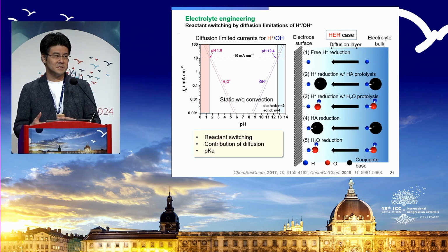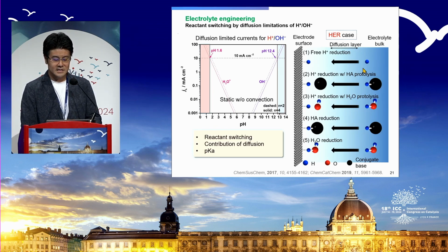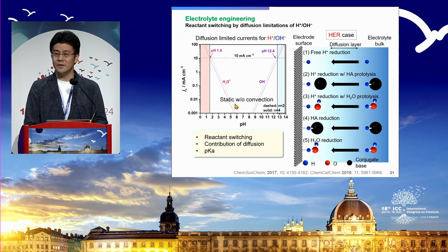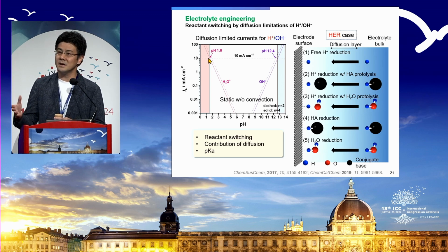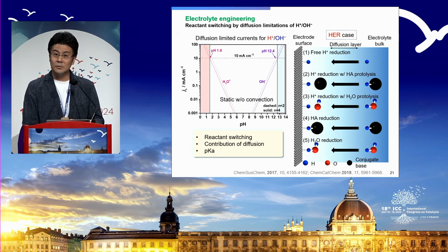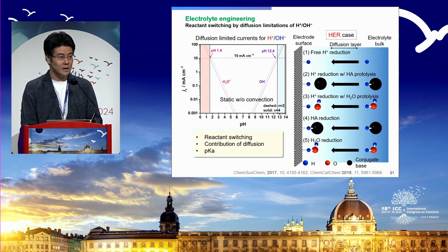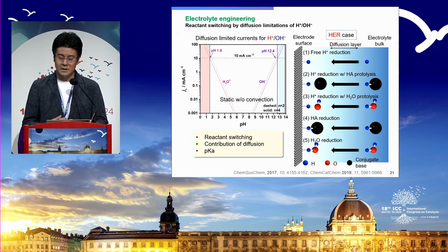If we learn these kinds of things, in the ideal case, it's completely static conditions without any convection. Actually, if you want to achieve this 10 milliamp per square centimeter that we say we want to achieve, then the proton concentration has to be pH 1.6 or even lower. Highly acidic condition can be the only condition that you can use. Likewise, if you want to maintain OH minus as a reactant from the bulk, the pH has to be larger than 12.4. So this white region is where I call non-extreme pH conditions, where proton or OH minus cannot be supplied.